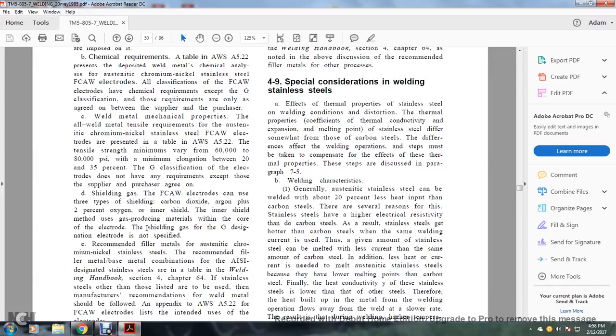Weld metal mechanical properties. The tensile requirements for the austenitic chromium, nickel, stainless steel flux cored arc welding electrodes are presented in the table of American Welding Society A5.22, with a minimum tensile strength varying from 60,000 to 80,000 psi and a minimum elongation between 20 and 35%. The G classification of the electrode does not have any of the requirements except for those supplied with the purchase and agreed upon.